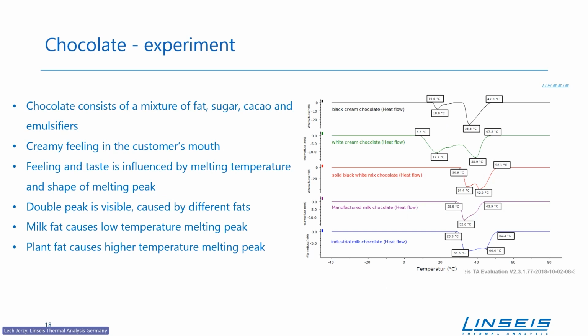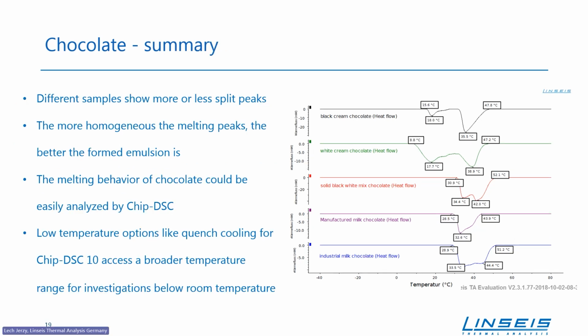And the result was different melting curves, and different types of chocolate yield different peaks. The curve shape reflects the composition of the product. Double peaks are also visible, caused by different fats. So we have a clear image that there are some differences between different kinds of chocolates. Due to the temperature range for this application, we recommend using one of our cooling options, quench cooling or intracooler, or liquid nitrogen cooling is also available. So we have more homogeneous peaks. The different samples show more or less split peaks.